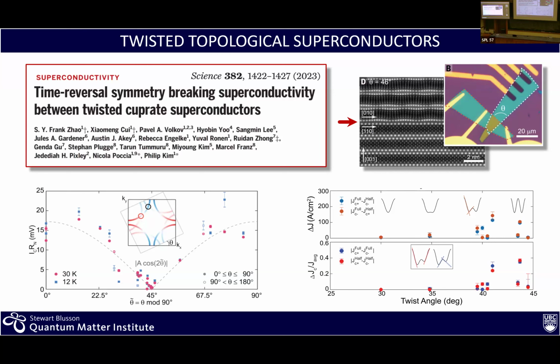And here you see a TEM image, which is really important, where you have one crystal and the second crystal. You see the structures are a little bit different for details of the structure of these materials, but then you can see a very clean interface between the two. And that's where the action really is. You need a very clean interface.